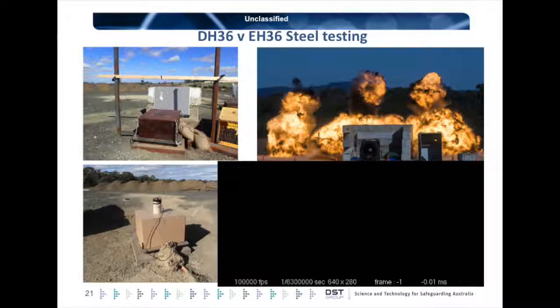This is the explosive charge sitting on that arrangement. There's a cardboard box around the steel plate. Probably in this situation, that steel plate was cooled down, maybe to minus 20 degrees, something like that, to retain the cold in the plate. But it also stands the explosive charge off away from the steel plate. You can do a number of these tests at one time, and hopefully, if the video's going, this is high-speed video showing an explosive bulge test. What we're trying to do here is capture, we've got sensors on the plate capturing the loading situation and so forth, and looking at the performance of that plate.